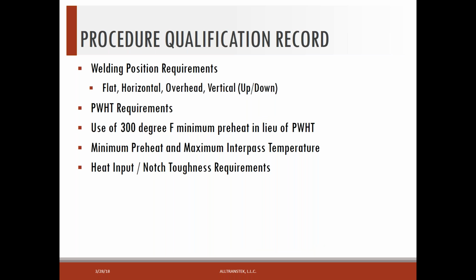Okay, so after we've welded the coupon and tested it, now we have to put together our procedure qualification records, and usually welding position only comes into play when we have notch toughness requirements. The reason I say that is if I don't have any notch toughness requirements specified, if I weld that coupon in the overhead position or the down flat position or the horizontal position, it doesn't really matter. The side bends or the testing of the side bends or the tensile test will not really be affected adversely by one position or the other.